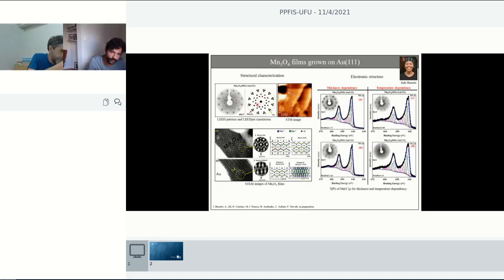And then we can look for the diffraction pattern and judge the structure of this film. We can look with the STM image where these atoms might be sitting. And we can also judge from the transmission electron microscope cross-section image which kind of structures we have, and combine all these three here to have a very robust model about this system. And then again, look for the peak positions. I think it's a nice example.